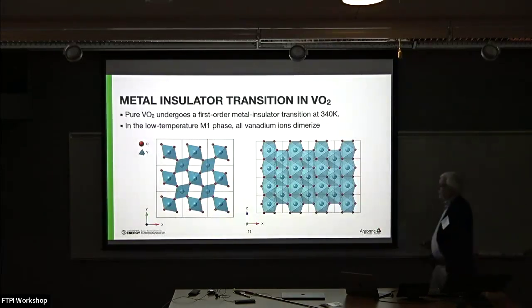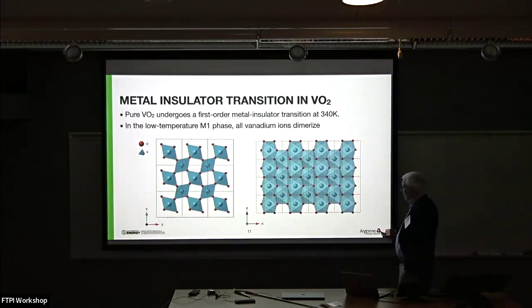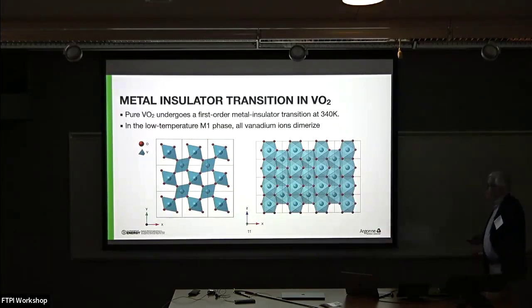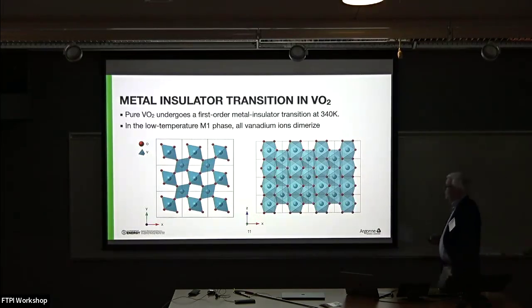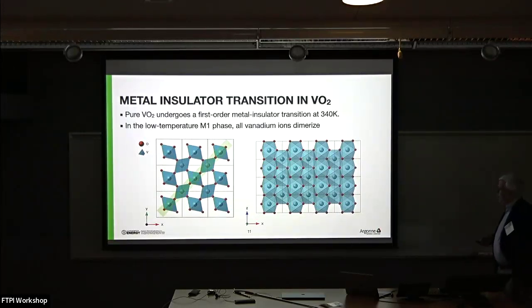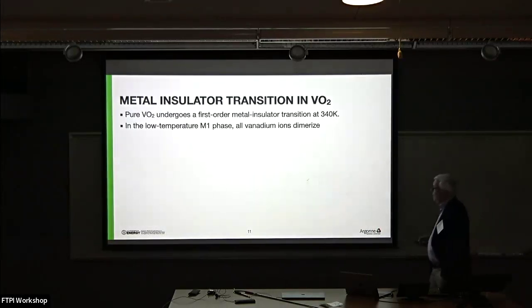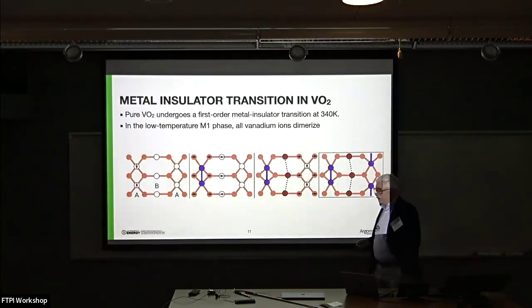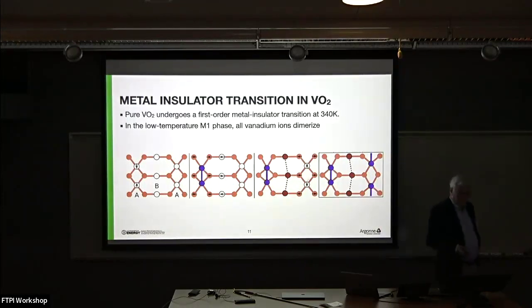So what about VO2? VO2 has a rutile structure. We have these edge-sharing octahedra along the c-axis, which are coupled along the 110 direction by these corner-sharing oxygens. And if you go along the 110 direction to look at that coupling, what's known to happen is that VO2 goes through a first order phase transition, as many of you will know, at about 340 Kelvin.